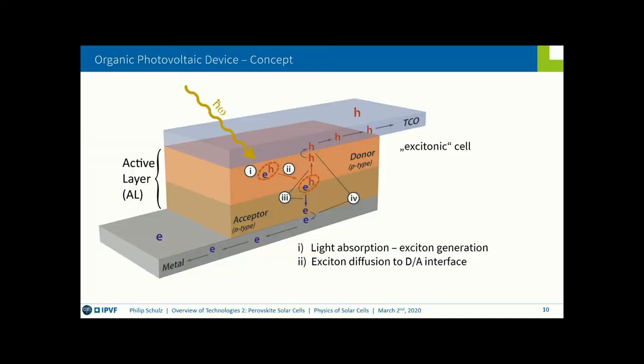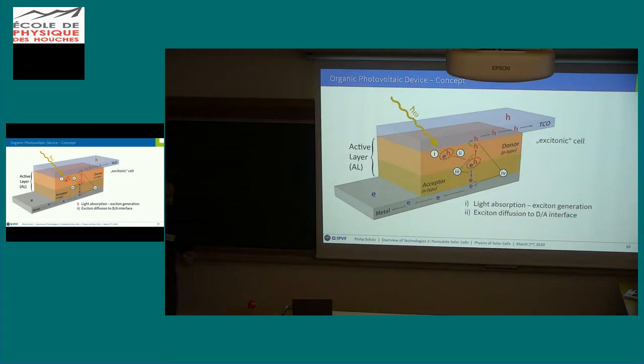After this, the exciton, which is electrically neutral, needs to diffuse to the interface between a p-type and an n-type organic material. In organic solar cells, we speak of the donor, usually a polymer, and an acceptor-like molecule. Over there, the excitons can dissociate, and you have now these separated carriers that are again transported as free carriers throughout the solar cell and make it to the cell contacts, where ideally they are being collected at the interface.